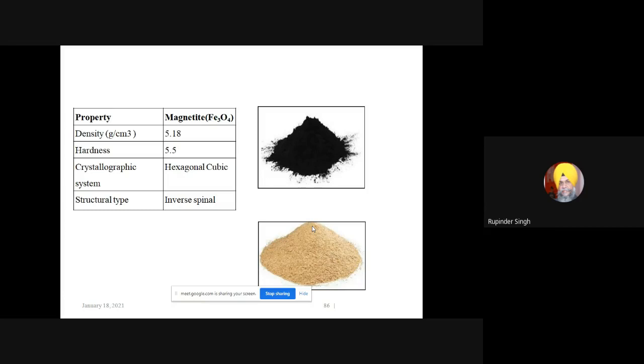So what we did is we selected PLA as a biocompatible polymer, which was reinforced with PVC, and then to have properties like wood, we used wood dust, and to have some magnetic effect of a self-assembly type nature for 4D, we reinforced it with some magnetite powder. Based on this, we selected different compositions of the material. Based on the composition, some parametric optimization using DOE on a twin screw extruder was made.